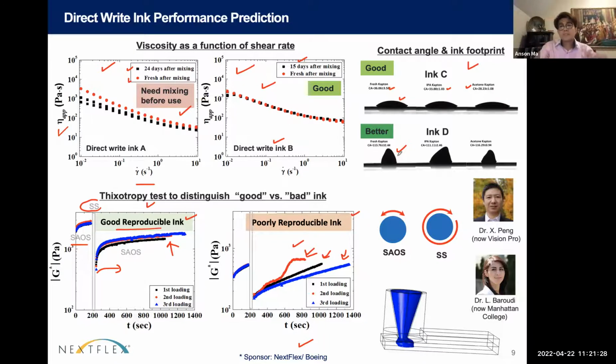Key point number two is that, in some inks, if you want to have very high resolution print, your actual ink D would be better, because you see this is all irregular shape, but the fact that it's irregular is because the viscosity, or there could even be some yield stress, is so high that when you deposit the material, it's not going to spread, right? So you can see the contact area is much smaller than the other ink C.